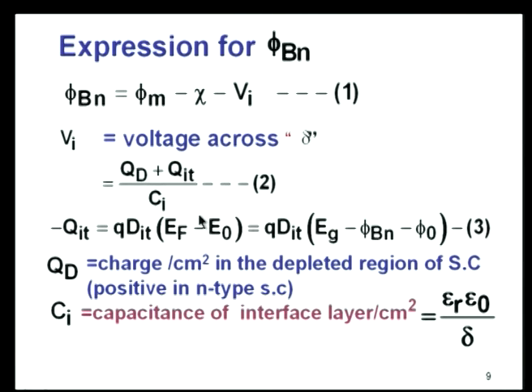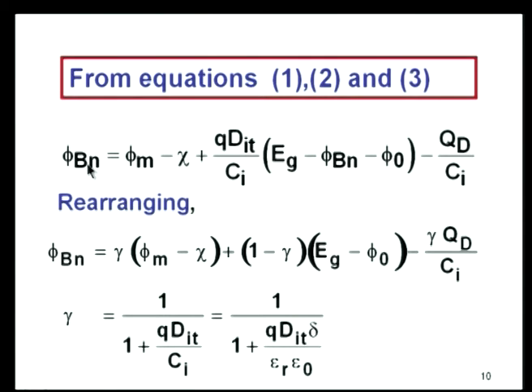So, let us go back and see the phi b n. Phi b n is phi m minus chi plus V I, this whole thing is V I, because this is plus Q D I, that is minus, Q D I by C I. This whole thing is minus. So, this minus stays with that plus charge. This charge is negative, so that becomes plus. So, Q D I T by C I into what you just now written. This is the V I due to D I T. Due to Q I T, this is that quantity. Q I T by C I is that quantity.